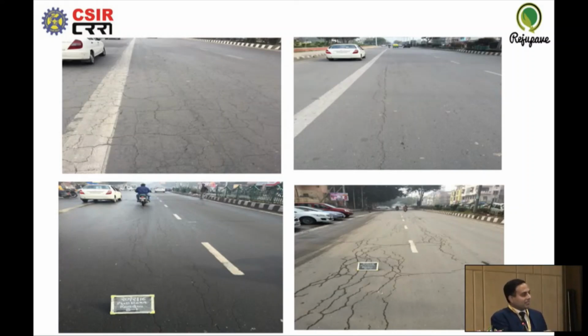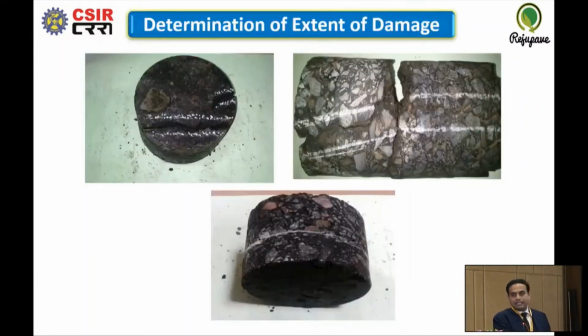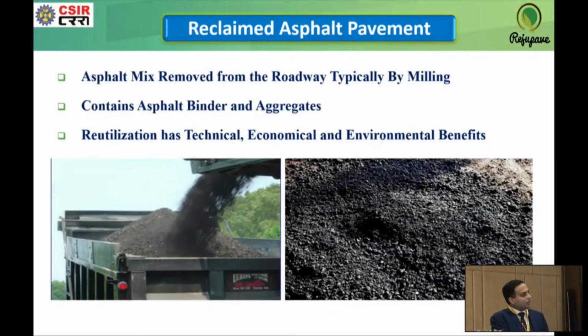We carried out extensive analysis by extracting bituminous cores to find out the quantum of distress and the depth of distress, whether it is limited to the surface course or has gone up to the dense bituminous macadam layer. Based upon that, we developed this entire study and extracted the bituminous material from the road surface. This is a glimpse of RAP, reclaimed asphalt pavement material extracted from the distressed bituminous pavement. It contains around 3.5% bituminous binder and a good quantity of natural aggregate.